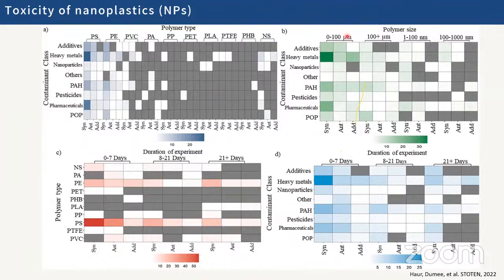Besides this, in many cases, there will be also limitations related to the fact that we can only assess microplastics down to maybe 10 to 15 micrometers. But the broad definition, which I really dislike very much, is that microplastics are defined as any plastic item of size less than 5 millimeters. But this is too broad, okay? Something at the milliscale, microscale, or nanoscale behaves differently. So we have to revise that definition. But you can see here that the majority of the reports are in the micron range. Some are in the hundreds of nanometers range, but very few, and hardly any are in the submicron level. Okay. So that's another challenge there.